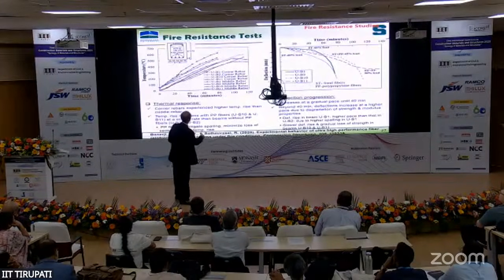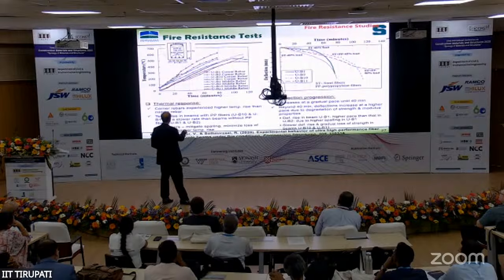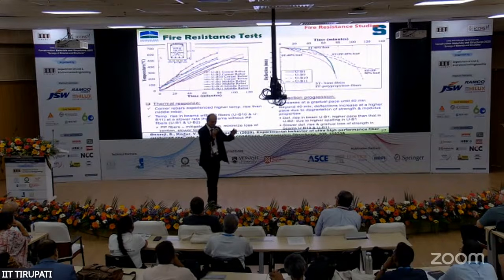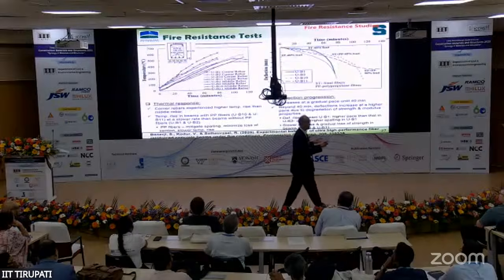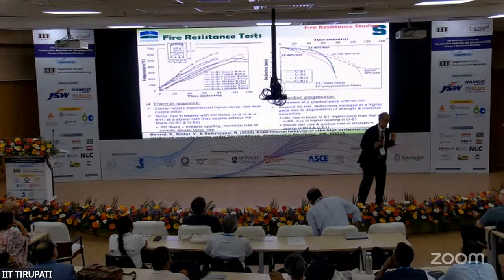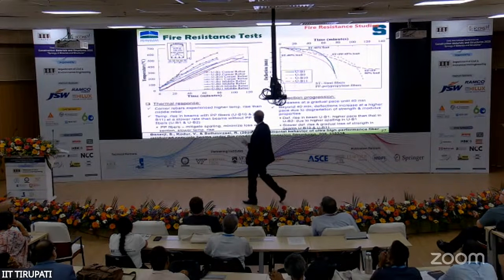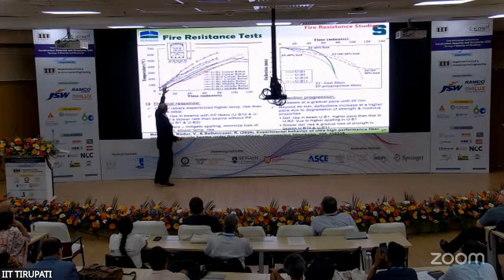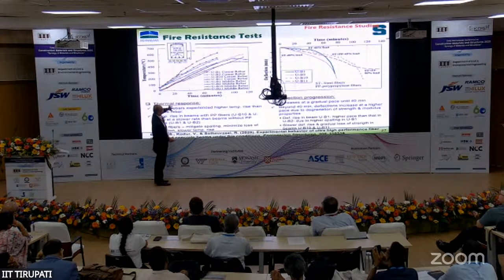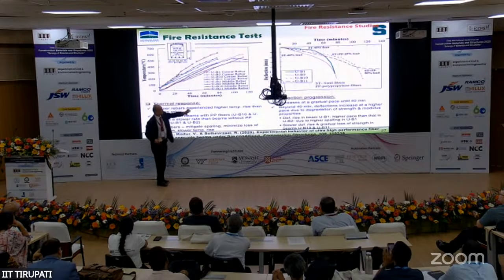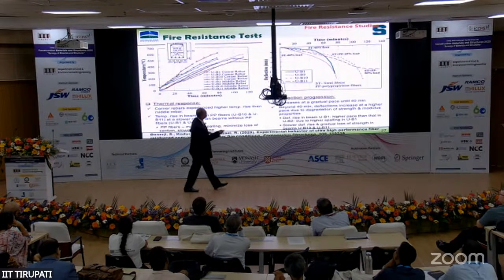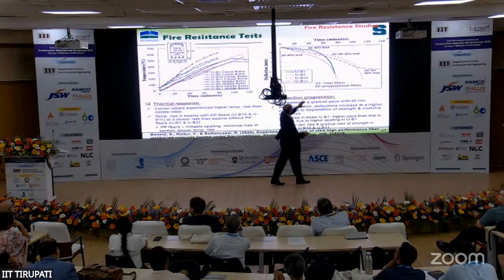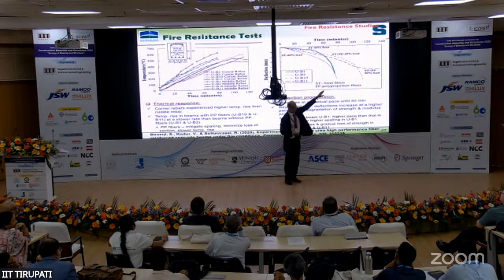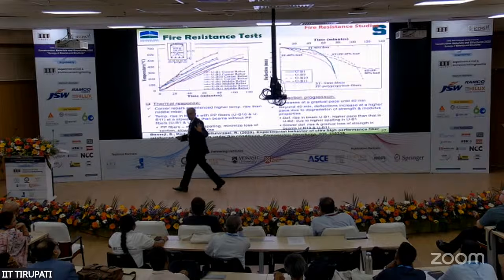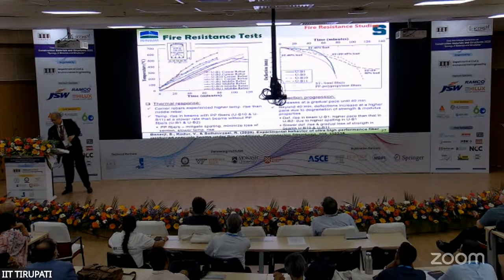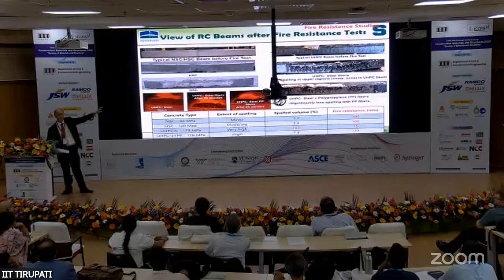For example, one of the thermal response of this, the corner rebar. In fact, in a concrete member, less effect on concrete. It's all how steel is structured, positioned from the fire point of view. When you have this, right? So you look at this, that corner rebar, it sees much more rapid rise in temperature than the middle rebars, okay? And this is the deflections of the beam. As you can see, if you add polypropylene fibers, it helps to some extent, the deflections, which I'm going to talk about. Then we did the tests, as you can see, right?